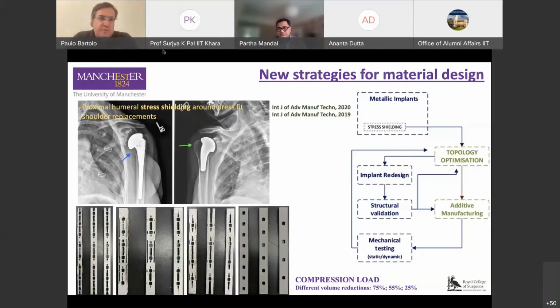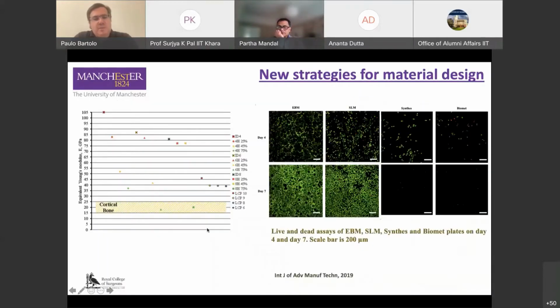So we use topology optimization. We consider different physiological loading conditions. We impose different volume reductions. And we achieve a couple of designs where it was possible to reduce the equivalent stiffness of the initial plates to a range of values within cortical bone. So we managed to solve the stress shielding problem. Those designs were produced using two different technologies: electron beam and laser-based powder bed fusion.